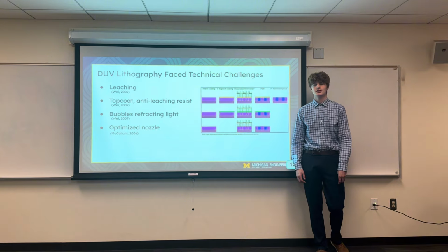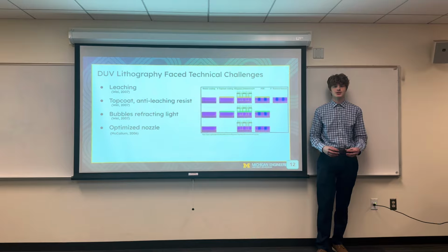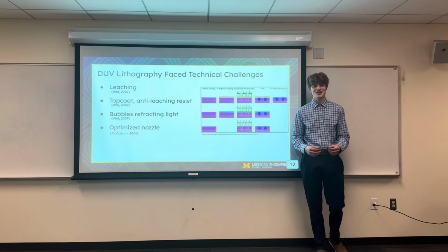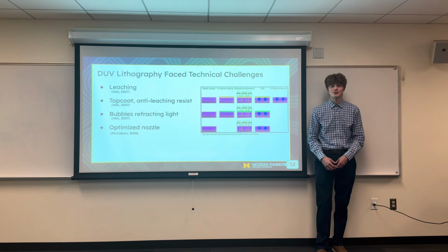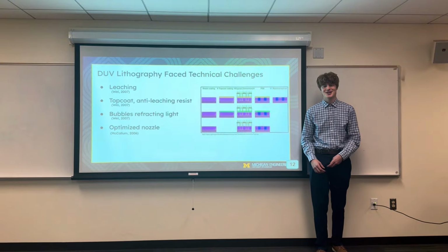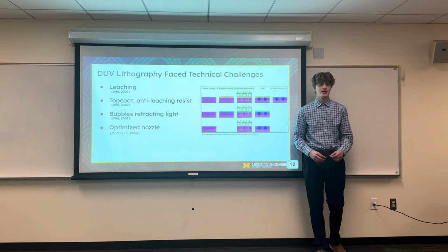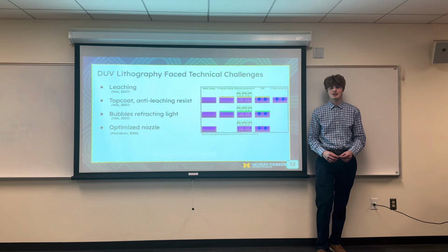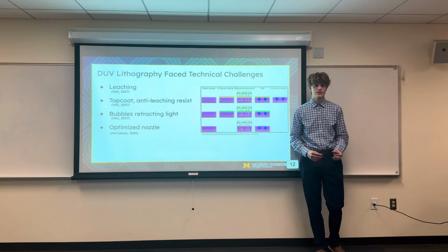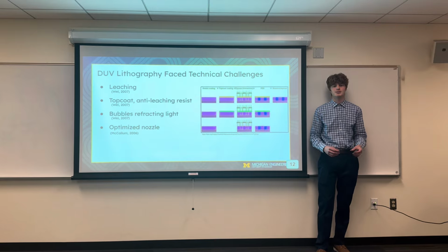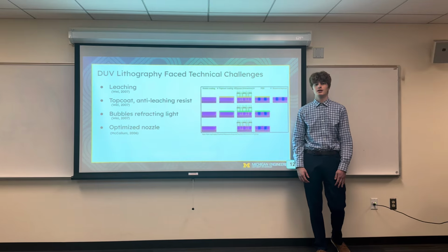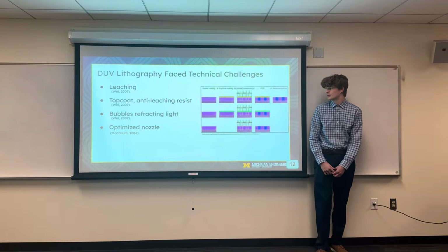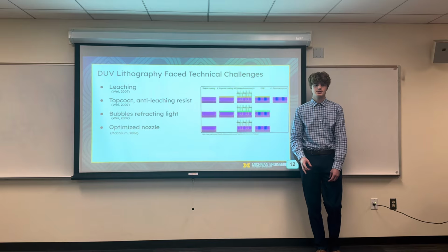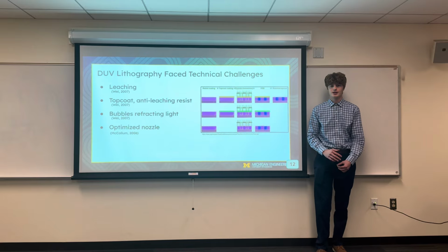So one challenge is that the microcomponents of the resist layer will leach into the water, contaminating it. And so one solution to this is to add a top coat layer on top of the resist layer made of hydrophobic polymers. However, a better solution is to incorporate these polymers directly into the resist layer, removing 2 steps to the process, which would be adding the top coat and removing it.